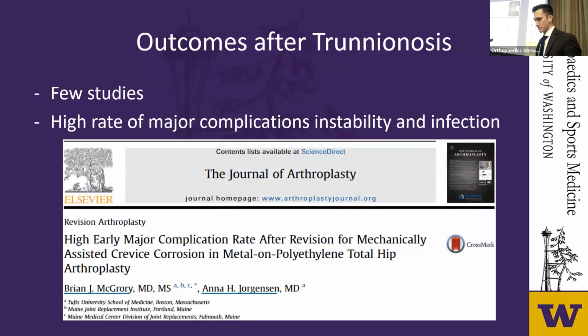Another retrospective case series, this one with 27 patients at a minimum of 6 months, again after revision for MARS. These folks again found high rates of dislocation with 6 out of 27 patients, and 3 of the patients experiencing deep infection after revision. Still though, on average, much improved Harris hip scores with 74% achieving a good or excellent outcome by that outcome metric.